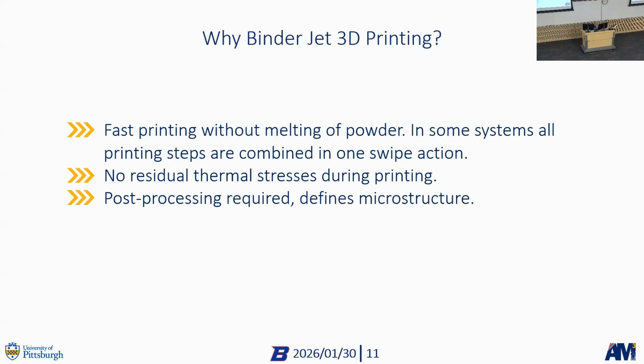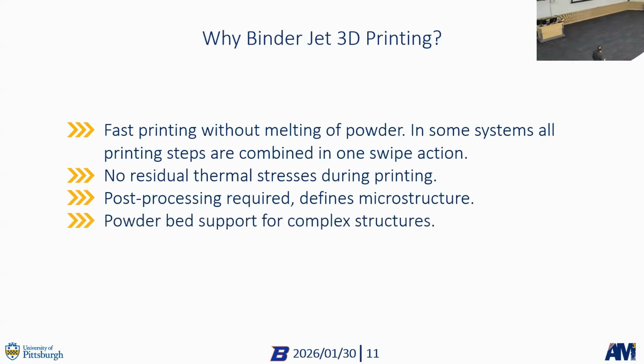But in powder metallurgy, and in Pennsylvania, there's a large amount of powder metallurgy companies out there. You need to do this as well, right? So this process is actually well understood in the industry, how to densify, how to sinter things from a powder. And since we have a powder bed throughout the build, we can actually build really complex structures with overhanging parts, flat parts over the entire layer, right? And they will not sag down or anything during printing, like in laser powder bed fusion, for example.